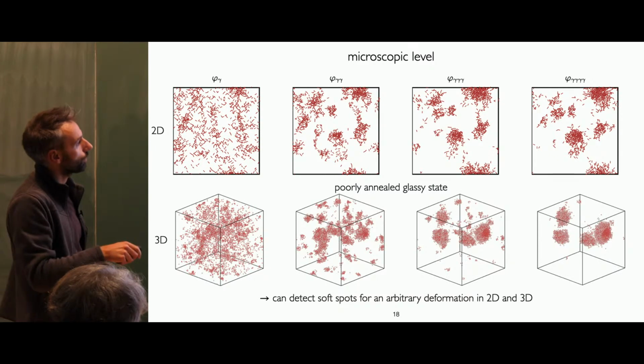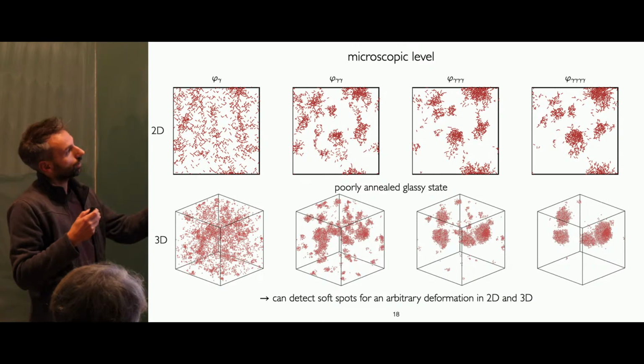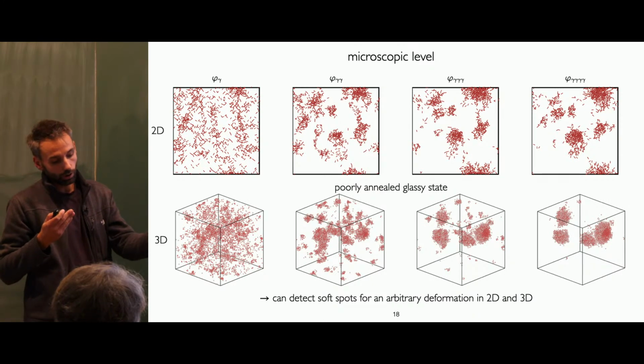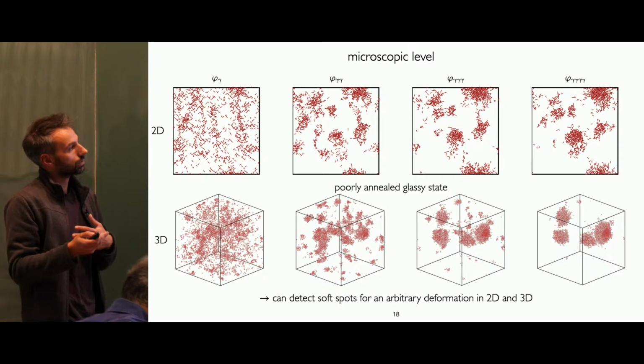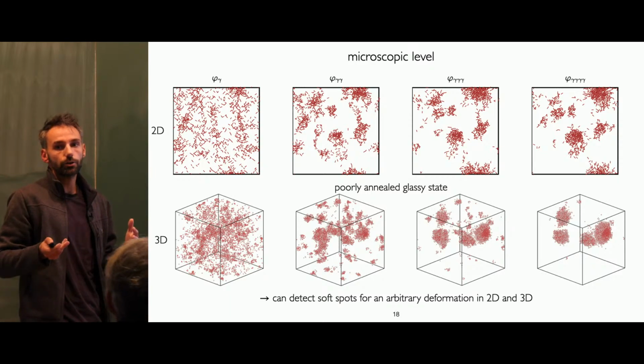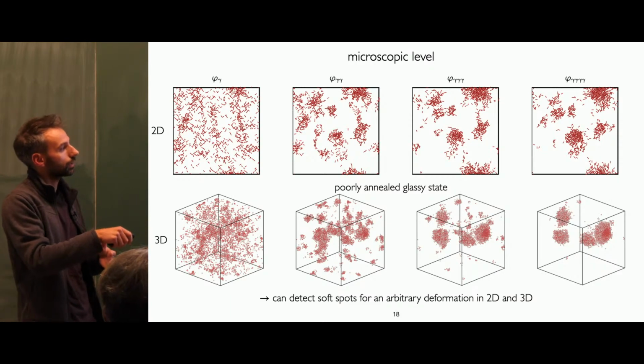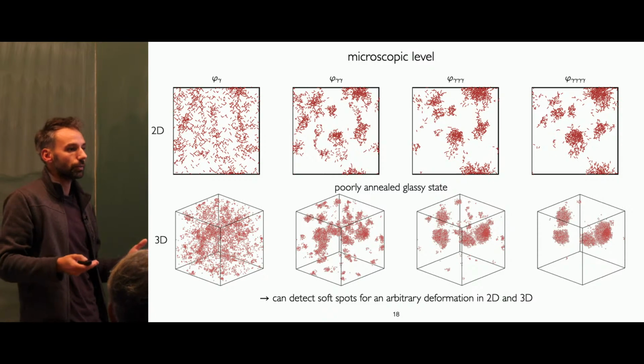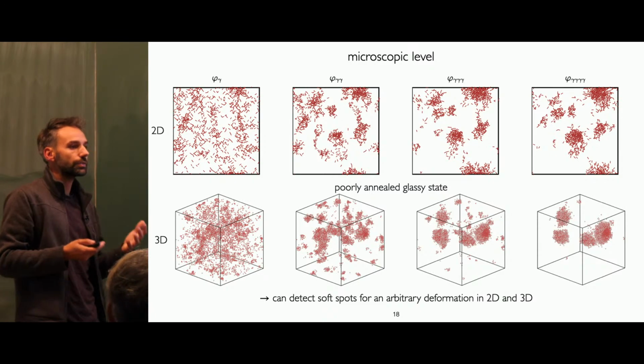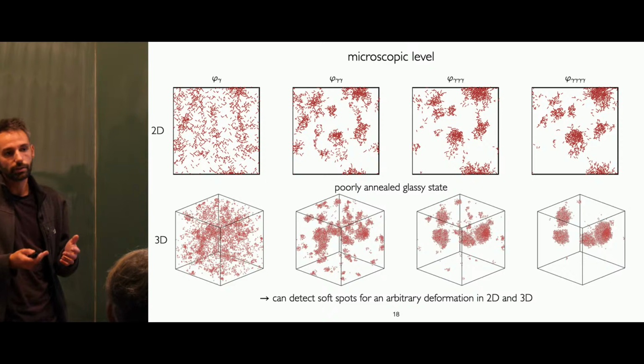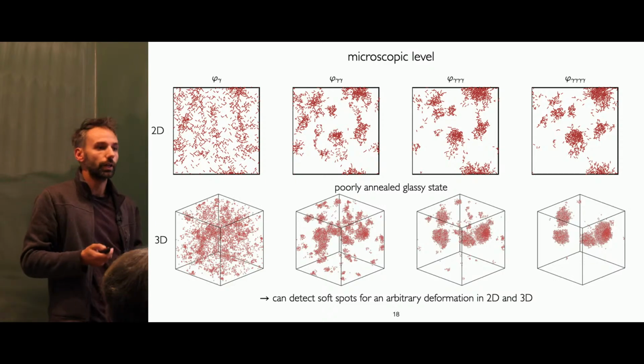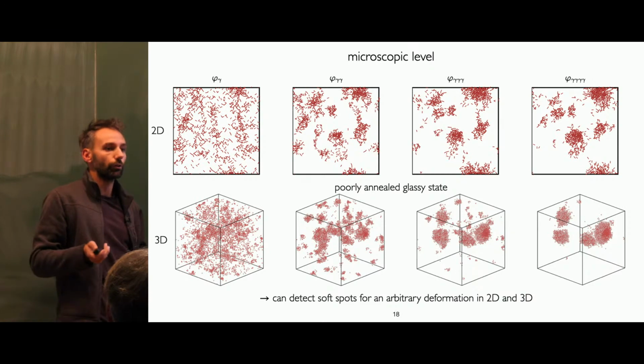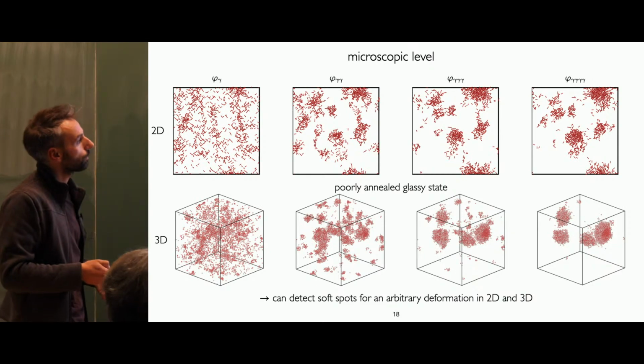And the advantage of the framework is that you only need to solve linear equations. You don't have to fully diagonalize the Hessian matrix of your system. So you can actually look at this in a real system in 3D. Most of the methods which are based typically on the landscape, you need to diagonalize your Hessian to get all the modes. And diagonalizing a Hessian when you have, I don't know, 250,000 particles, it's very tricky.